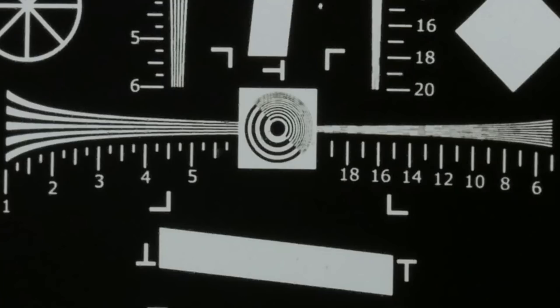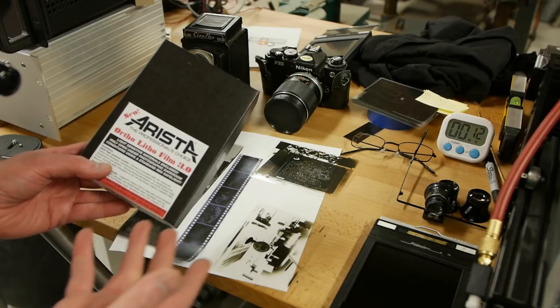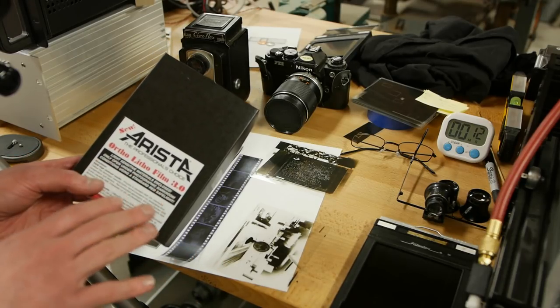One, it's very high resolution. Two, it's very high contrast. There's an anti-reflective coating on the back known as an anti-halation coating. And it's super high contrast, meaning that it goes from totally clear to totally dark, almost snapping over.